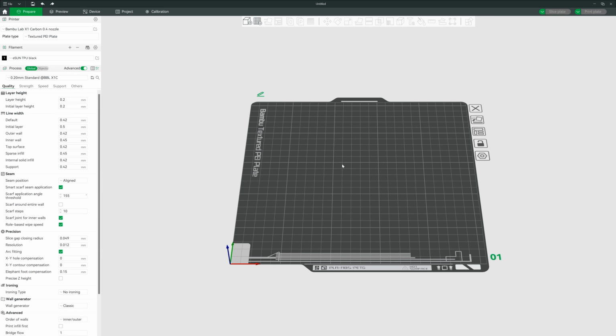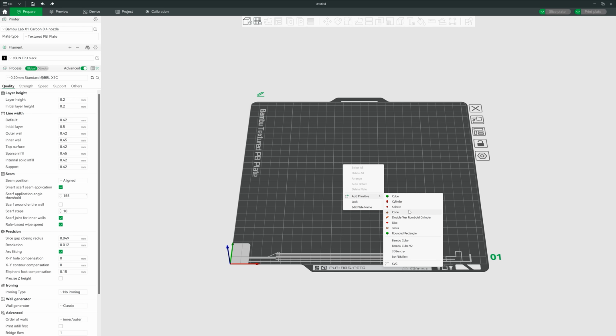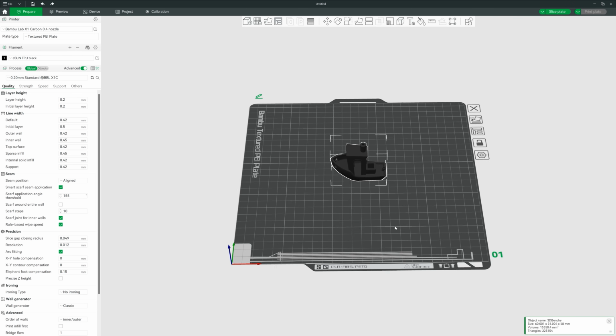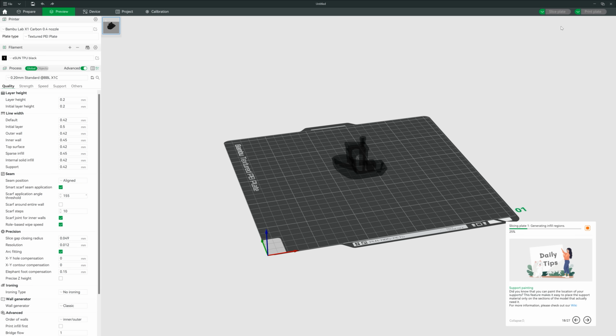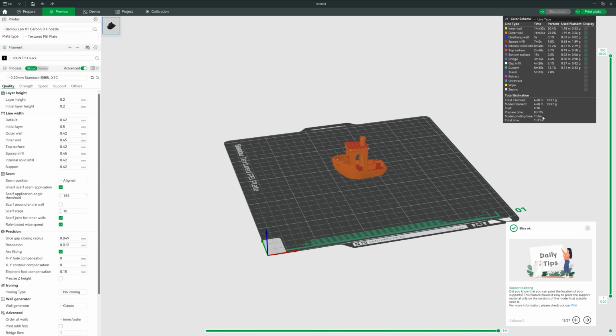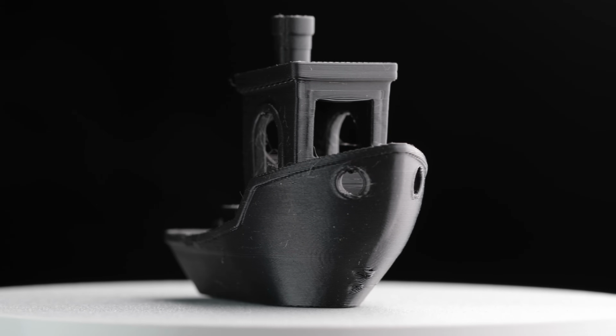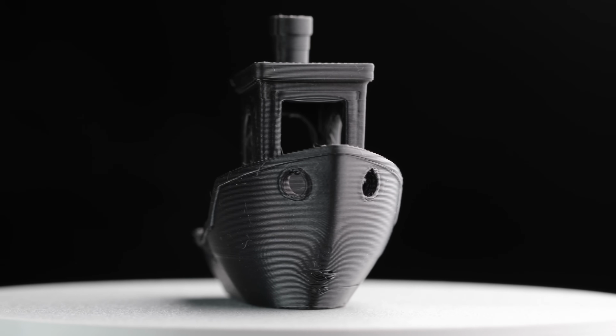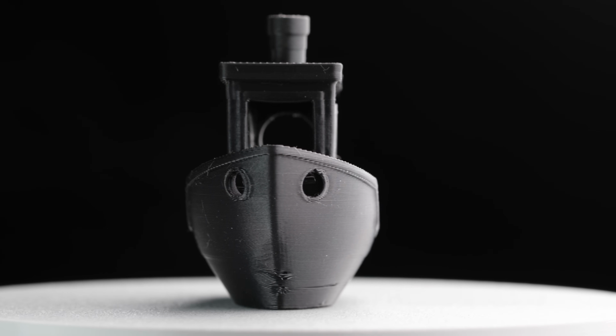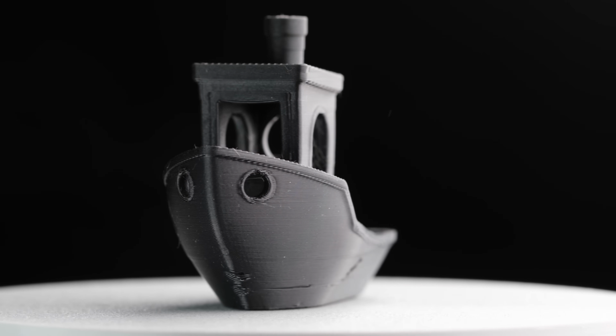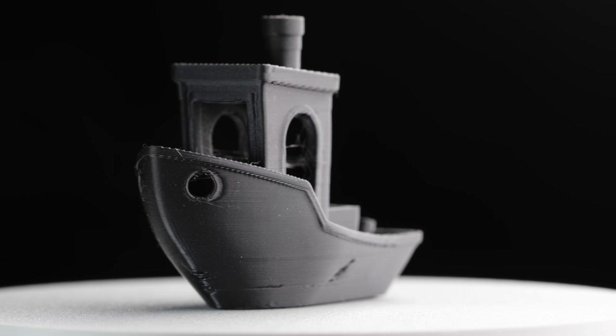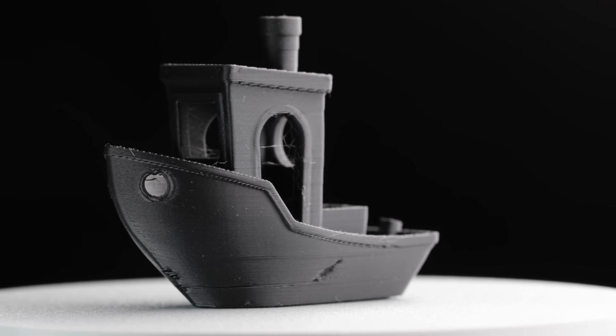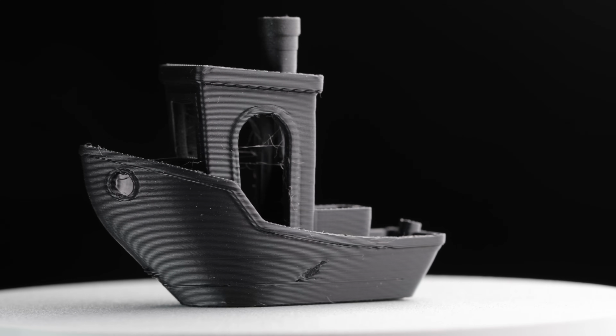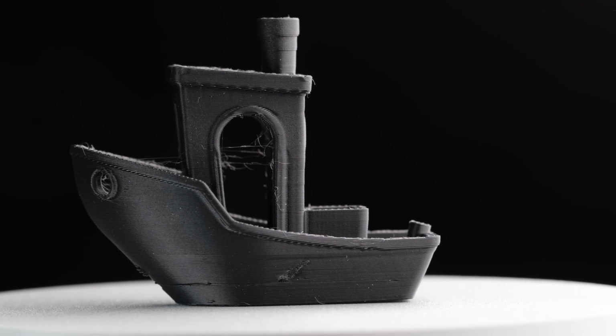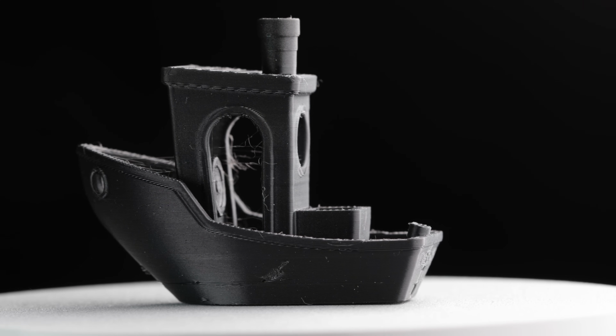Now let's put these settings to the test with another Benchy print. Using our new custom filament, the default 0.2mm profile and the correct spool settings, the print takes 1 hour and 11 minutes. And here is our third Benchy. Well, this looks bad. We've got dents at the bow again, and some stringing around the cabin. The bow issue isn't new, we have seen it before. The problem: we are printing too fast and the filament isn't sticking properly.